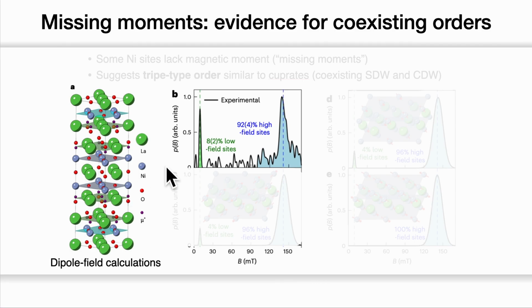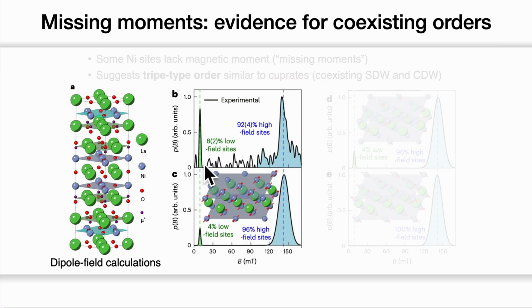Okay, now we would like to explain the experimental data result. As you saw in the previous slide, we show fast precessing and slow precessing components. If we use the magnetic structure like this figure in the nickel oxide plane, we have some missing magnetic moments for some nickel atoms to form this spin wave pattern. Then we can reproduce the experimental observation.